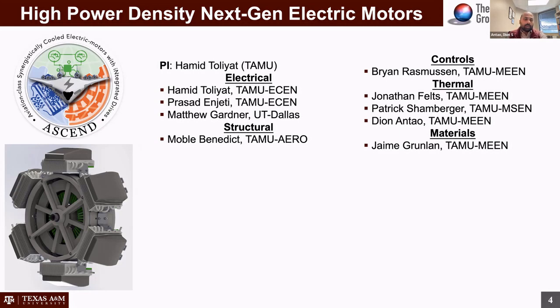What you see at the bottom left of this slide is a mock-up of what the motor looks like. I didn't put a scale bar here intentionally because the design is still in flux to a certain extent. We just got into phase 2 of this project, and so we have to actually build this full scale motor. It's roughly, I would say, about 1 foot in radius at the most, and it can produce power on the order of about 250 kilowatt, which is required for flight, at least takeoff conditions.